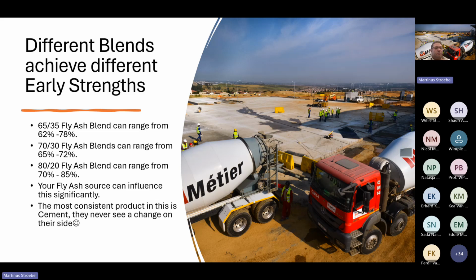Then on fly ash, it's quite difficult if you do not get your ash from one source. We at Métier try to only use one source. It makes life a lot easier to manage and control performance. Typically, the early strength performance between a Class F and a Class C is also vastly different. The typical history that we get, if you use a Class F, you can sit around about 60%, 65% at 7 days, and the old unclassified Class C, you sit around about 75% at 7 days. But we design accordingly to guarantee our 28-day strengths.